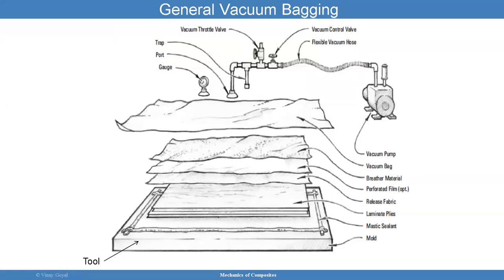We have the general vacuum bagging process, and this is old school. So you have the tool, you have the laminates, and then you have your release fabric, and then you have the breather material, which allows uniform application of pressure, and then you have your vacuum bag and the vacuum pump. This vacuum bag is sealed down on these edges, where you can see there's tape, usually double-sided tape, and then you pull the vacuum and ensure that the vacuum bag can hold the vacuum and that everything is well put together.